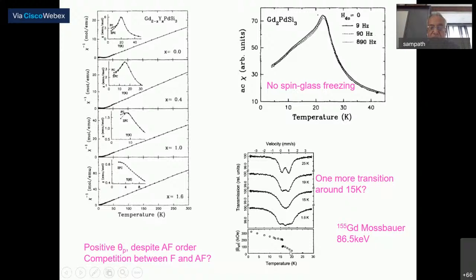When I visited there, you could see very clear evidence for the loss of magnetic hyperfine splitting around 21 Kelvin. This established that this compound orders magnetically at 21 Kelvin. So now, though theta is positive, it orders antiferromagnetically, and that means a strong competition between ferromagnetic and antiferromagnetic interaction in this material.